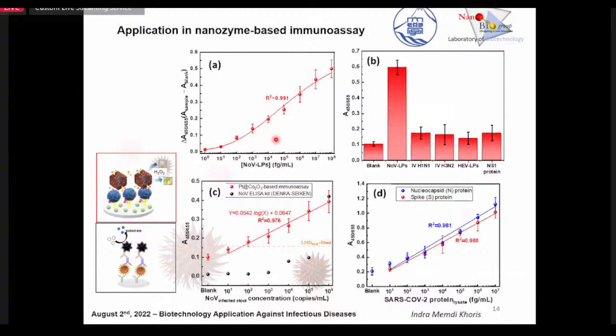Further, and lastly, the most important thing, we can detect norovirus. We can go directly to the C, the clinical norovirus isolated from humans. We can compare our results to a commercial kit from a local company in Japan, and it shows higher, wider linear calibrations with higher sensitivity compared to the ELISA kit on the same concept of immunoassay, but using a different enzyme and nanoenzymes. Selectivity on the B side shows only norovirus detection: only because of the presence of norovirus will it change color, not with other proteins or viruses.